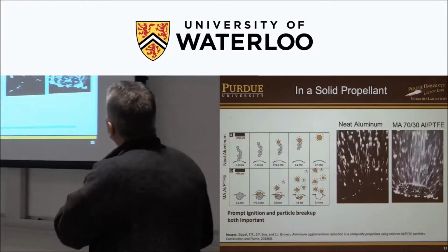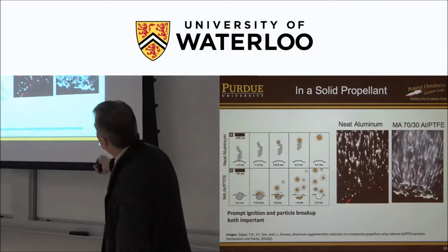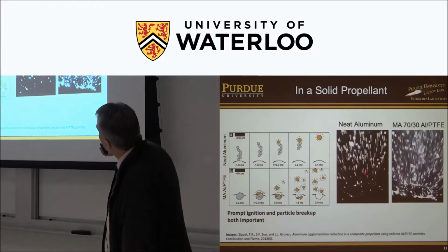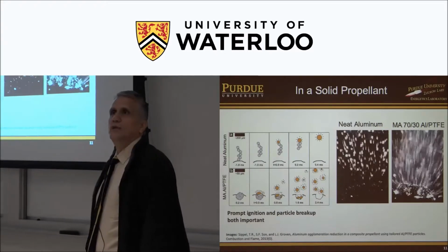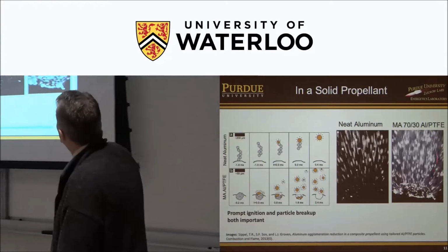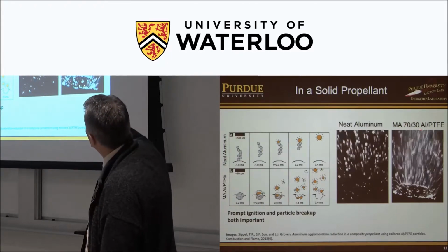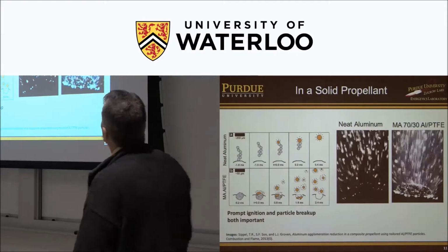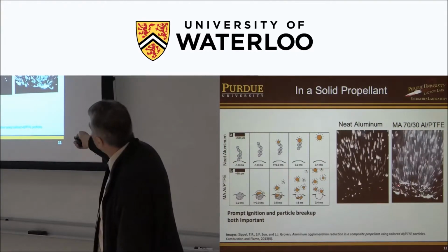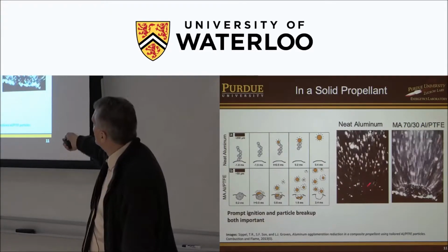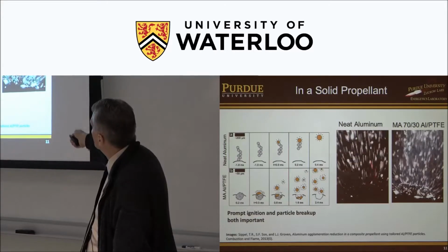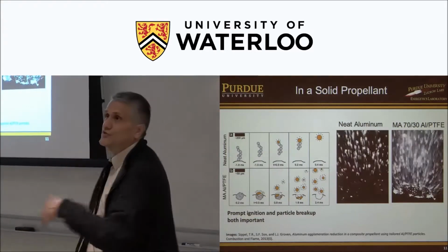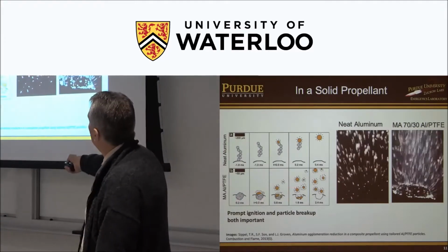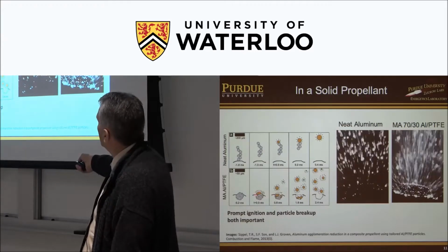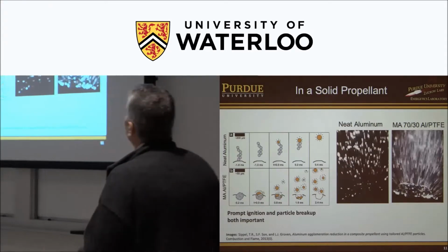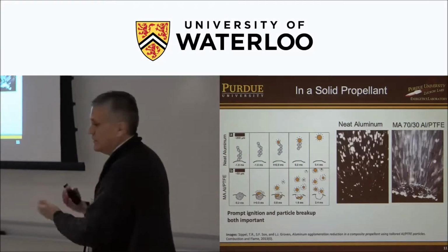So if we put that into propellants, this is the baseline aluminized propellant. This is the surface, if you look closely here. You can see these particles. Some of these particles you can see tails. That's alumina smoke coming off from that particle. And this is what we call mechanically activated 70-30. So 70% aluminum, 30% PTFE or Teflon. If you look at the surface, there's a lot more bright spots. It's igniting right at the surface rather than as it regresses down and then ignites. And you also see a lot more streaking. That means there are small particles. So what's happened is these composite particles ignite more readily at the surface, break apart into smaller particles, and that's, like I said, going to improve the burning rate.